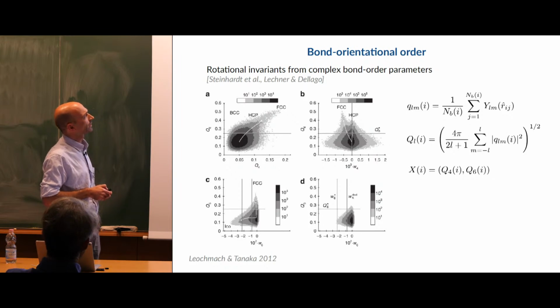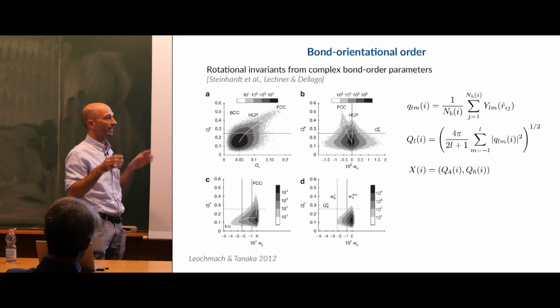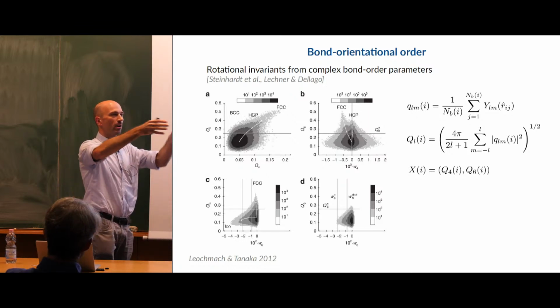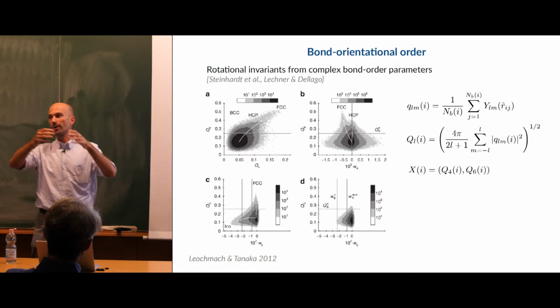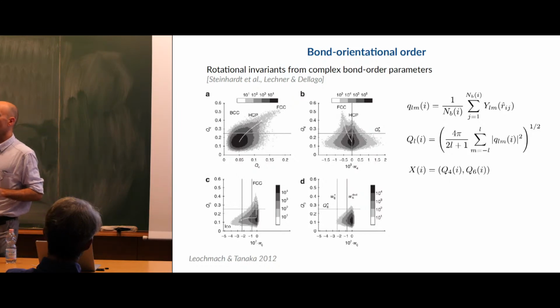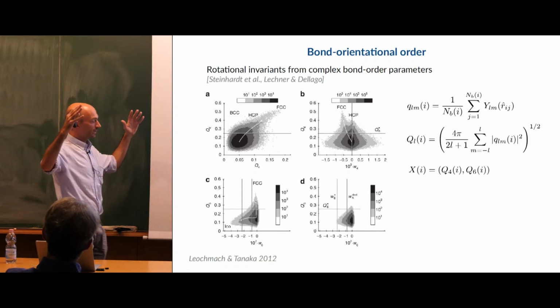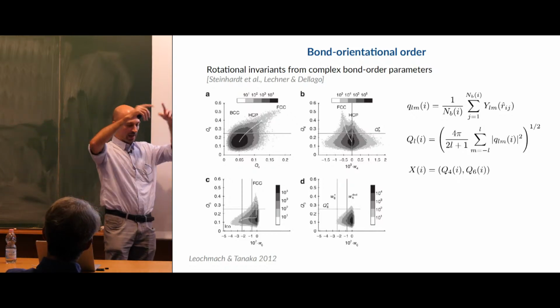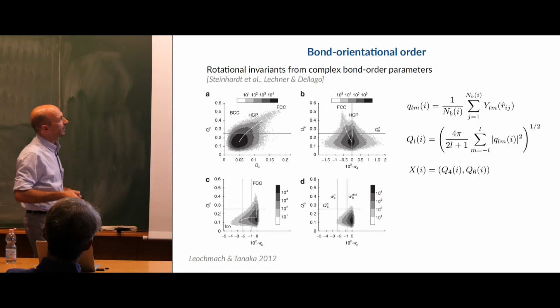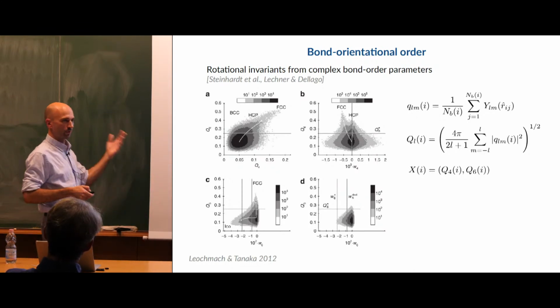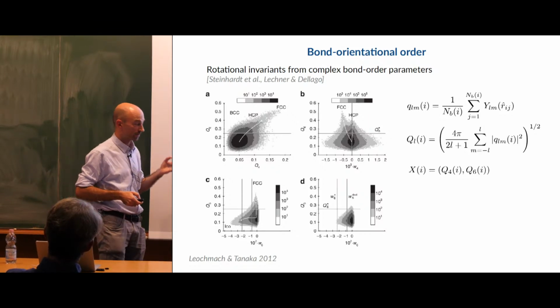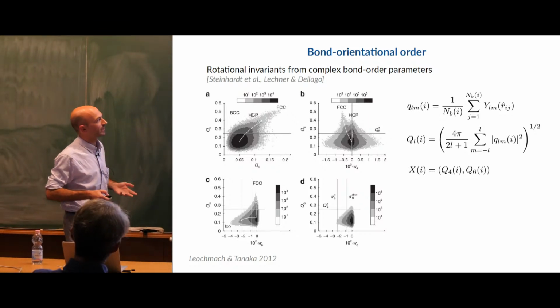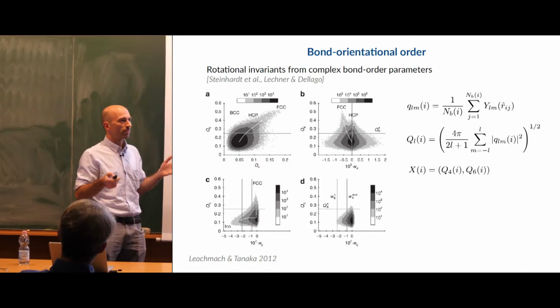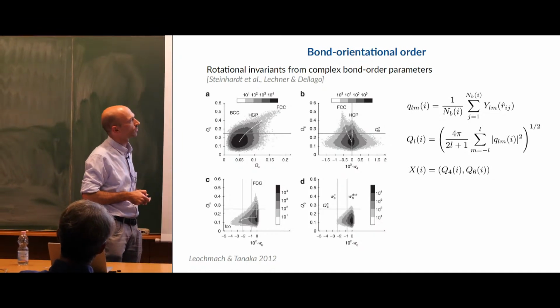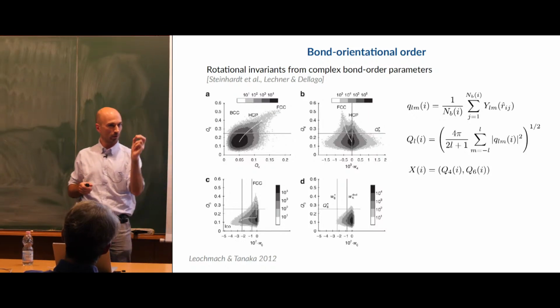So this is based on a definition of neighbors of a particle that has some sort of sharpness. Okay, you say the neighbors of a particle are those that are within a distance which corresponds to the first minimum of the g of r. Okay, and those are your neighbors. Then you project these positions on a unit radius sphere and make an expansion in spherical harmonics and then construct rotational invariants. Okay, this is the procedure, but it's based on a sharp definition of neighbors. And then physical intuition tells you that if you have a dense system, you should probably look at invariants of order 6, of order 4, and this gives you a descriptor of the local structure.